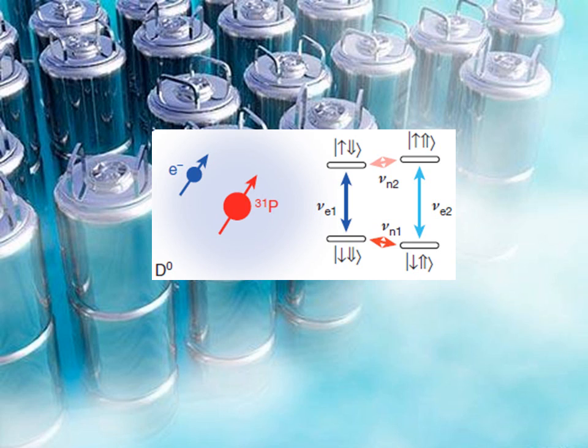Above cryogenic temperatures, this two-qubit system encounters a problem, because above 10 Kelvin, the nuclear spin qubit loses its long coherence times, and above about 30 Kelvin, the phosphorus donor atoms start to ionize, which of course ruins any system that is built assuring this two-qubit system, such as one that requires single-shot readout, which will be important later.